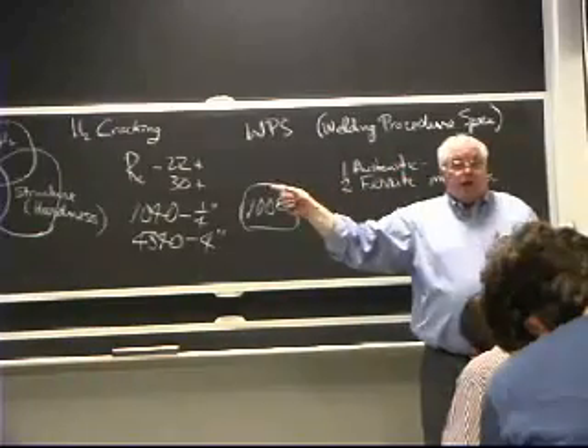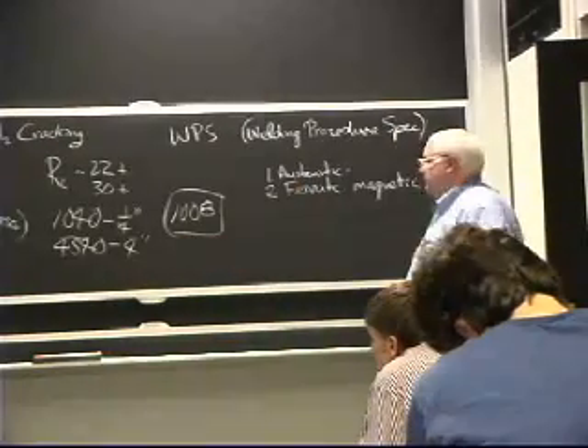And ferritic steels have the same crystal structure as your regular carbon steel, only they have lots of chrome, so they're difficult to weld, and you have to worry about hydrogen cracking. Okay, just like you had that. Here, there's no hydrogen problem.